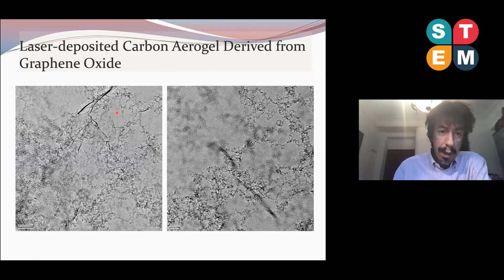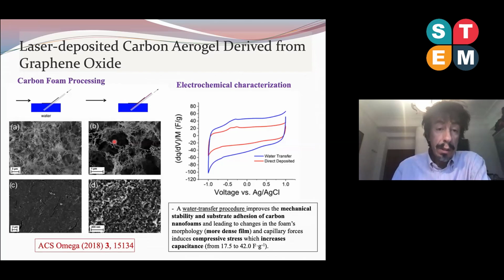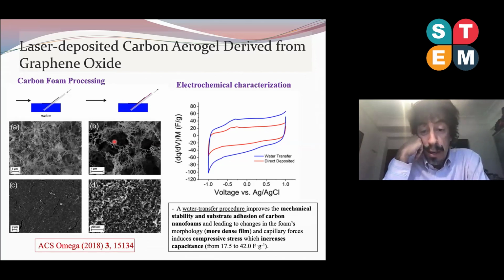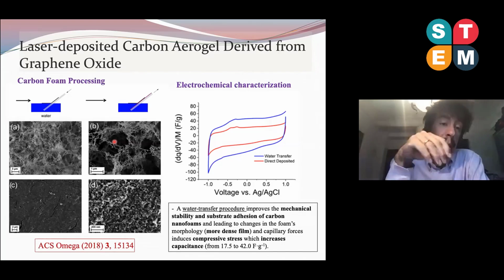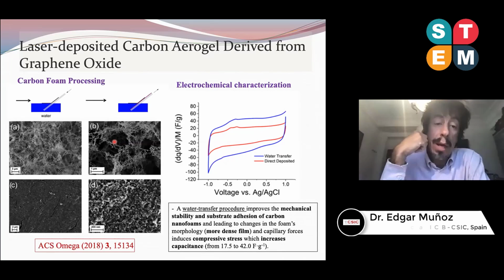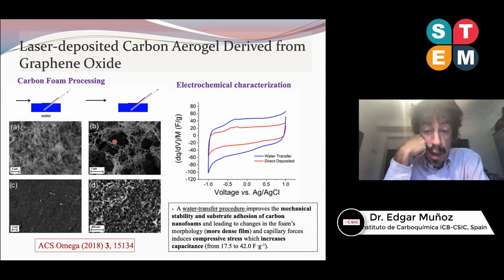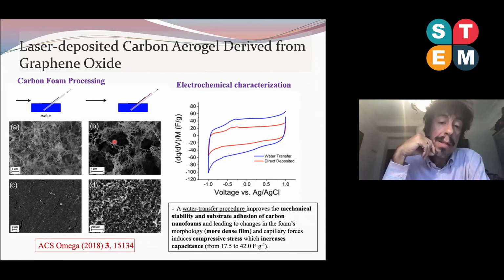Eventually, you can see graphene oxide platelets that were ejected during the laser ablation process. These materials exhibit very poor stability and poor substrate adhesion. But if we immerse them in water, and when we take them out again with another substrate, this material becomes more dense, and capillary forces induce compressive stress, which makes this material easier to handle and to manipulate.